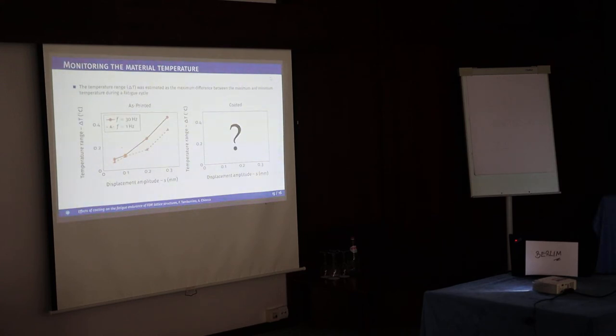This is done for one Hertz frequency and then we went up to 30 Hertz. You can see the shift in the same result - the maximum minimum temperature on the surface of the specimen. The results can be summarized - I'm sorry but we still don't have the coating results. We wanted to do this some weeks before the conference, but you know probably better than me, from an experimental point of view things can go wrong quite easily. We only have the as-printed results. As you can see, also logically probably, increasing the displacement amplitude during fatigue loading, the temperature range on the surface is increasing, and it is increasing more if we increase the frequency. This is kind of a logical result, but I wanted to compare some coated results that I don't have, and I'm sorry for this.